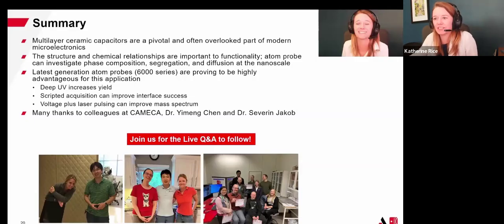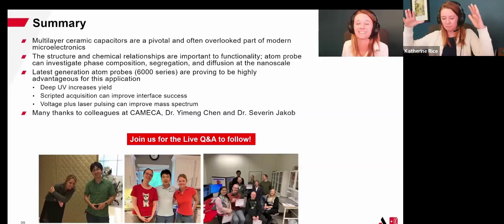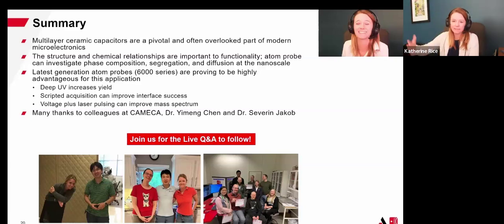All right, first question, I think it's for me. On the segregation slide, could the nickel diffusion be caused by FIB preparation? Now, this is a good question because when we're doing that annular mill process, we are pushing ions around. Now, the FIB-induced damage typically depends on the energy that you're using for that annular mill. It typically doesn't extend too far, even as knock-on damage.